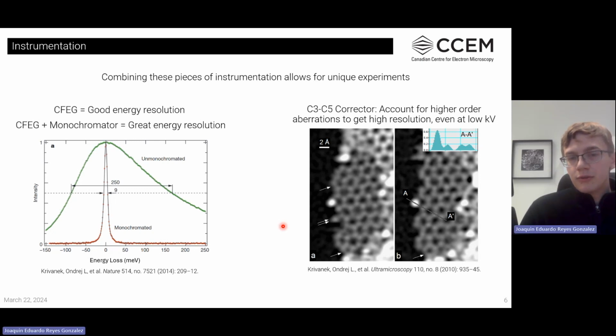If you have the C3, C5 corrector, you're getting great spatial resolution no matter what. If you take these and you put them together, then you have really opened the door to do a lot of very fine analysis. You're now getting the very high spatial resolution from that corrector, and you're getting that really fine energy resolution out of your gun and monochromator. So it's really by combining these two aspects that we're able to do this very advanced, very unique STEM analysis, giving us both high spatial and high energy resolution out of our instrumentation.